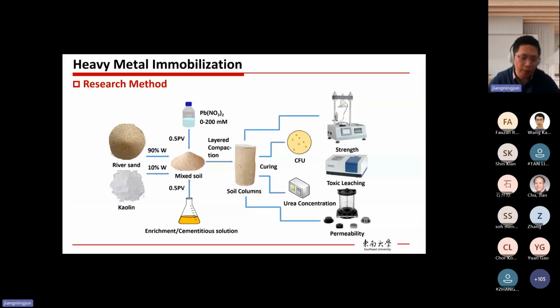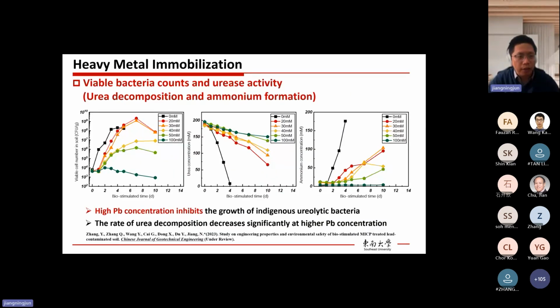After that, the samples were cured for a certain period of time before they were subjected to strength, toxic leaching, permeability tests, as well as CFU and urea concentration measurement. So firstly, here are the results about the bacterial and ureolytic activity change with time during the biostimulation process. For the first graph, we can see that for the no contaminant case, the black one, the bacteria grows very quickly, and after 4 days it reaches the peak, more than 10 to the 8 CFU per gram of soil.